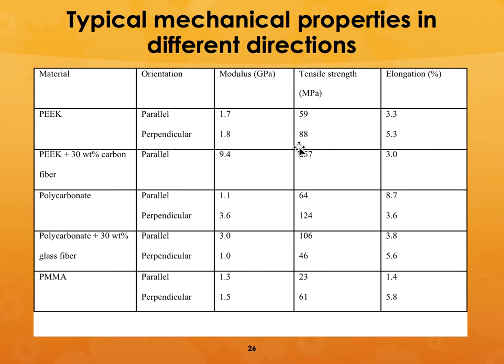So you can see that if you reinforce them, if you have no reinforcement, see the tensile strength, 59 megapascals. But if you reinforce them with 30 wt% carbon fibers, see the strength. It's 257. So it is 5 times the strength of this material. And with very similar elongation, so very similar strain. And see the modulus improvement from almost 2 to 9.4. With polycarbonate also, the improvement is not that high, but still there is significant improvement.